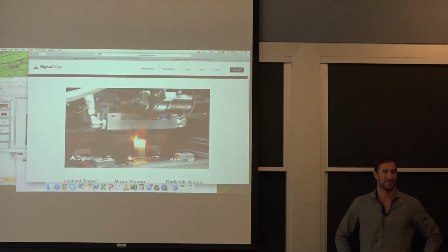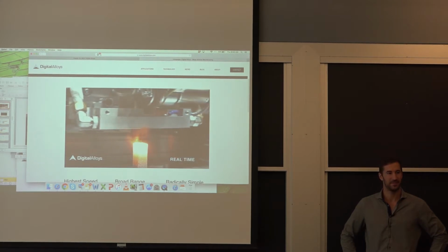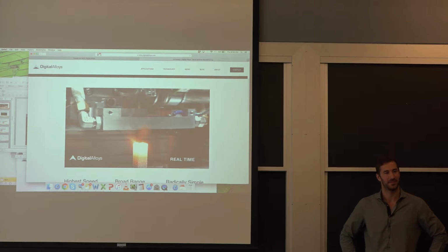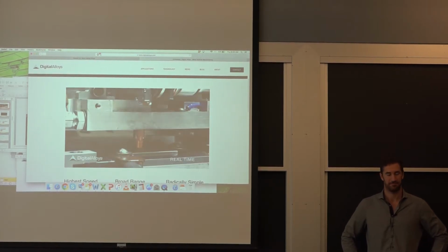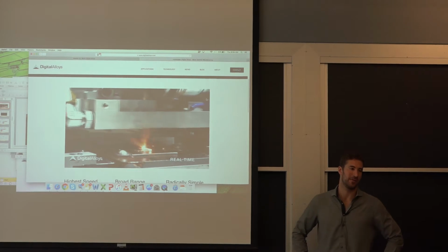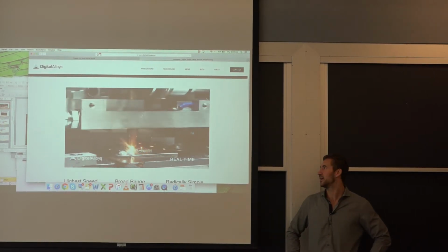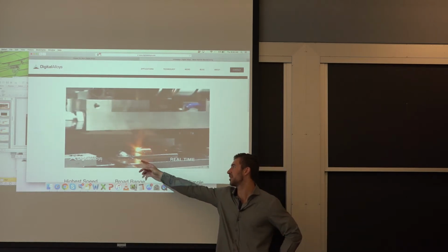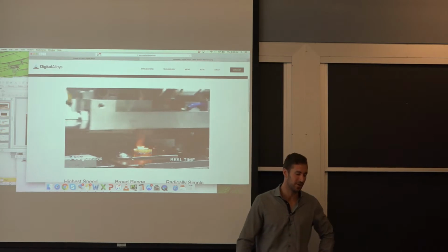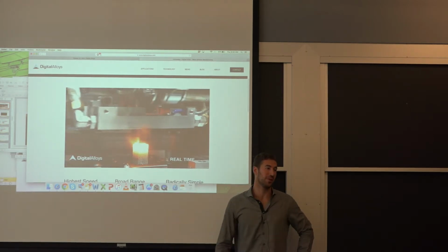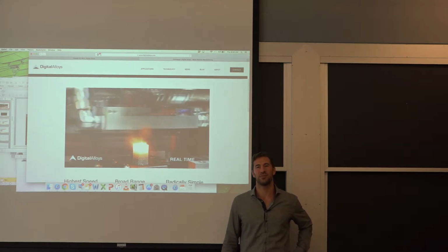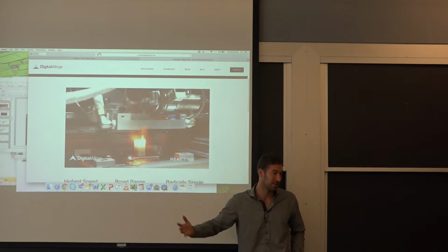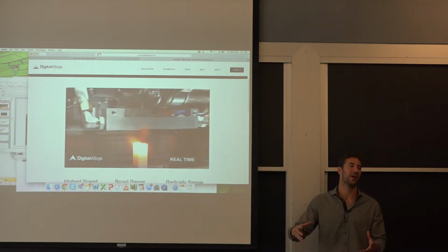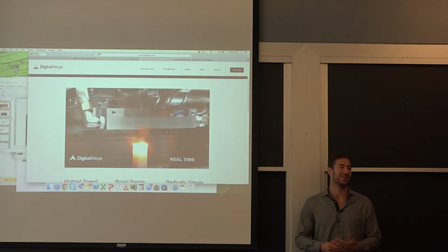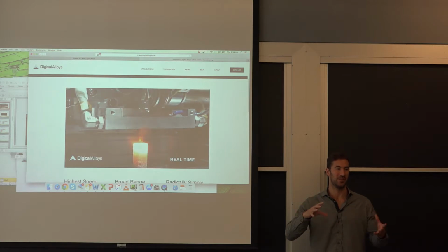And then, as you can see, it gets very hot on top, and titanium has a very low thermal conductivity. So do you have any issues getting the heat out of the part? You could have some super long, narrow part that just stays super hot and doesn't shed heat. Yeah, it's a big part of our development right now, figuring out thermal management. What you see here is what we call printing on a cold plate, so it's just room temperature, ambient environment. It's really hard to get good fusion to a cold plate with molten metal. So we're playing with ideas like, do you heat up the plate? Do you heat up the whole chamber to maintain that thermal environment and reduce the thermal gradients? Frankly, we're still figuring it out, and it's very geometry specific, like you said.